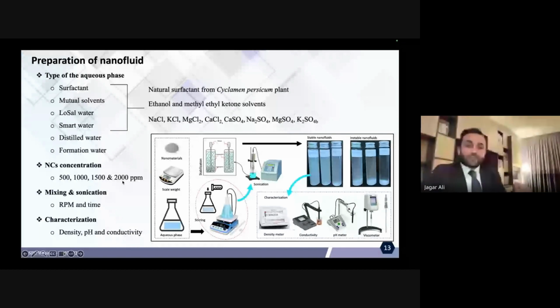This is the method and the procedure that we usually use to prepare the nanofluids. We can mix them using sonication, and then we should be careful about the stability of the nanocomposite. Sonication is used in order to mix the nanoparticles well, to be sure that we have good dispersion over time. So usually we use different concentrations of 500, 1000, 1500, and 2000 ppm of the nanoparticles. And when we prepare the nanofluid solution, we do some tests and measurements for the density, conductivity, pH, and viscosity.